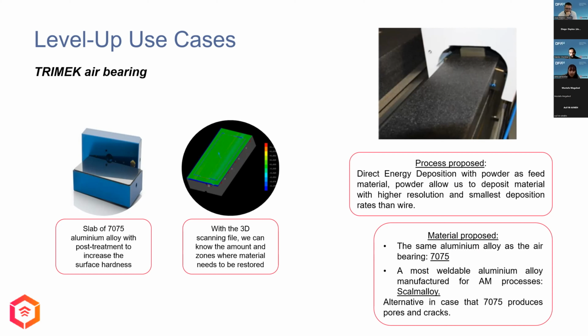The process proposed was to apply a coating of material to the work surface using direct energy deposition with powder, which brings better resolution to the manufacturing. The materials proposed were the same material as the bearing, 7075 aluminum alloy, and a more suitable alloy for welding, commercially known as Scalmalloy. The reason is that 7075 is described as non-weldable in all the materials handbooks.